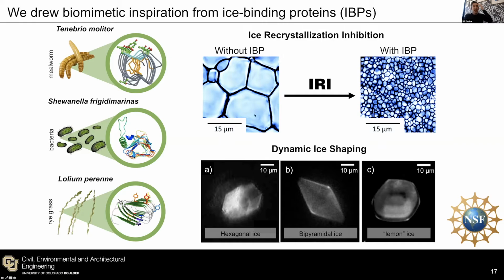So what you're looking at here are ice crystal grains without the protein, but with the protein, the ice crystal grains are kept really small. A lot of minerals and ice likes to grow from small crystals into larger crystals to coalesce. It's thermodynamically favored, and the ice binding proteins just simply prevent that by binding to the surface. The second mechanism we can observe is that when these ice binding proteins bind to the surface, they can change the shape of the ice crystal.